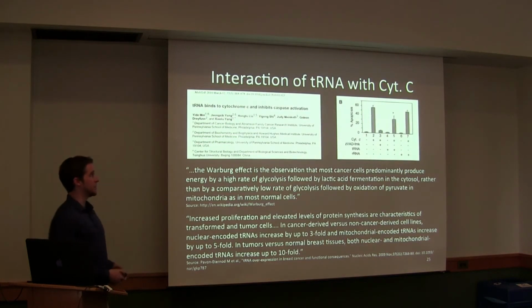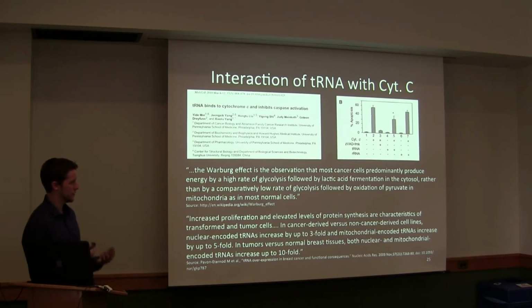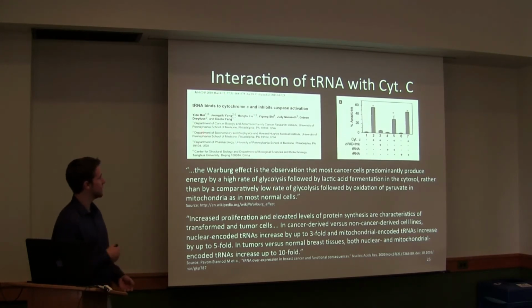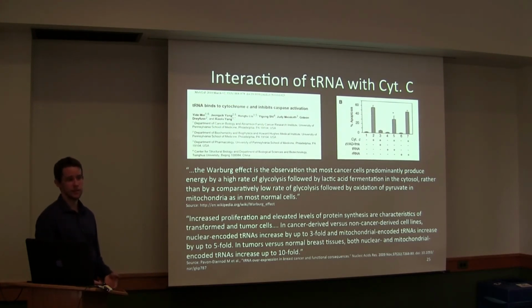And that becomes very interesting because tRNA has a known interaction with cytochrome C, which is involved in both cell respiration, producing energy aerobically, and also with cell death. It's normally in the mitochondria, and it is part of a cycle to produce energy for the cell. But when cell death is induced, it gets released from the mitochondria and triggers a chain that causes cell death. And tRNA is known to bind to cytochrome C, and if you introduce tRNA into cells, there's a statistically significant decrease in apoptosis. And so perhaps this movement of tRNA into the nucleus is some mechanism to prevent this interaction during cell death.